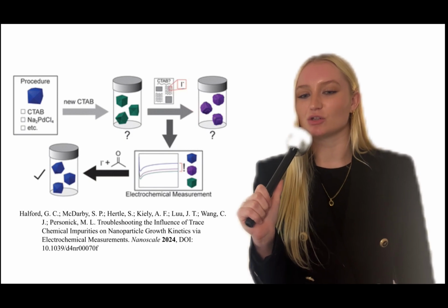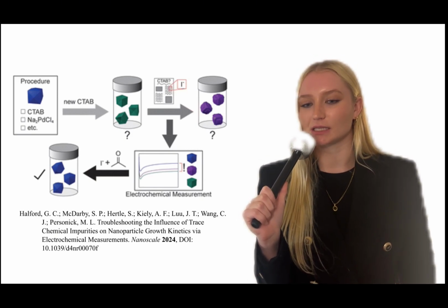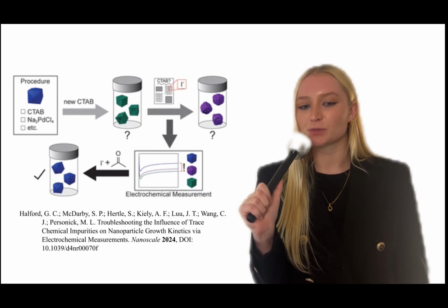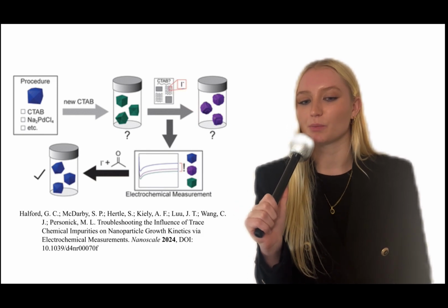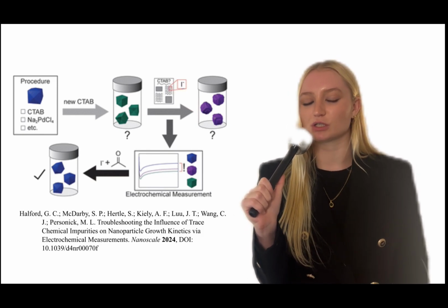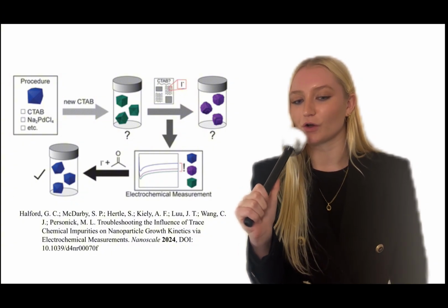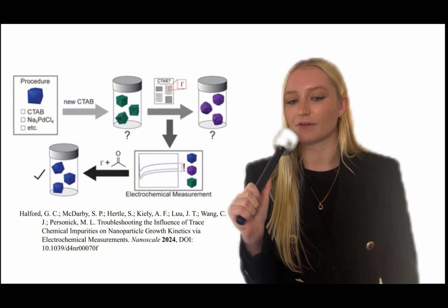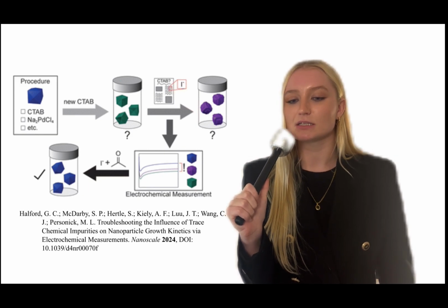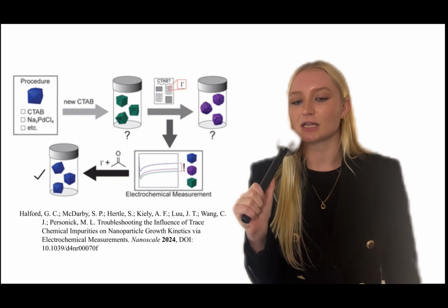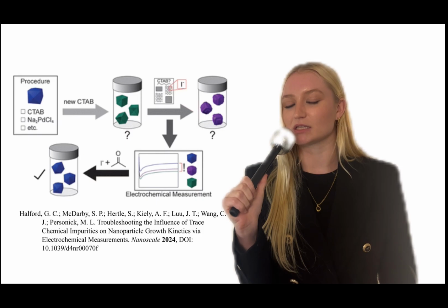Subsequent papers have continued to address multiple additives in the colloidal synthesis of gold nanoparticles. Halford observed deviations in expected nanoparticle shape when different bromide surfactant product lines were used to make palladium tetrahexahedral nanoparticles. Morphologies were corrected by adding known volumes of organic solvent back to their surfactant after evaporating impurities. This raises questions on the effect of solvents, suggesting that micelle formation impacts the reaction rates of nanoparticle growth.